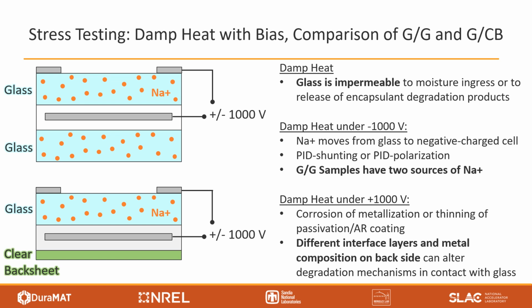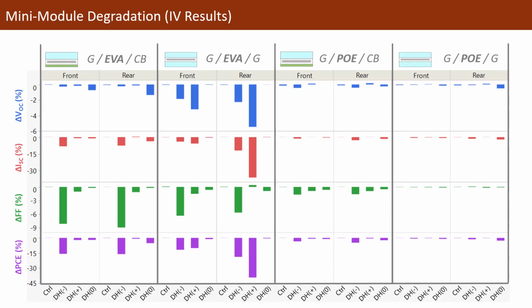Under positive bias damp heat, a different type of corrosive PID has been suggested to take place, where samples having rear side glass might be more susceptible. This corrosive mechanism could affect the metallization or the rear side stack, including the passivation and the anti-reflection layers. With that said, here are results for changes in IV metrics that we recorded both on the front side and